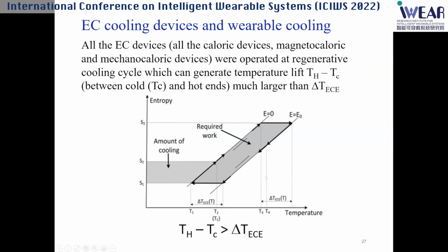So here are some examples. Let me just skip this one. Basically, all those EC cooling devices work on some kind of regenerative cycle, and this means using this cycle, the temperature lift between hot and cold end can be larger than the delta T EC. So this means if the delta T EC is 15 degrees, we could get cooling of 50 Kelvin, right? So the question is, can we do that?